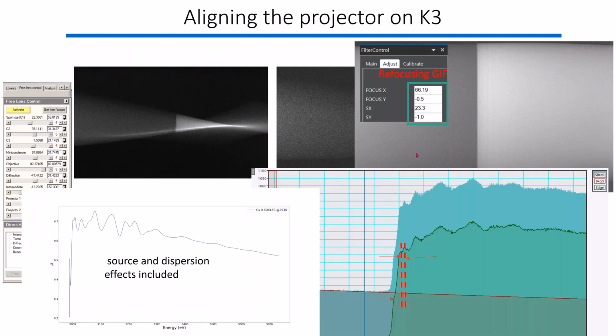And if you compare this to the simulation, we did the simulation to include the electron source as well as the dispersion effect from the camera and the optical settings we're choosing. From here, you can see the near edge information quite properly, but you can also see the oscillation properly, which is very much consistent with what we simulated for the extended fine structure. But now our focus is more on the extended fine structure, where the near edge information is not our concern for the moment, especially for the K-shell information. We want to get the vibrational properties and so on, so we care much less about near edge information.